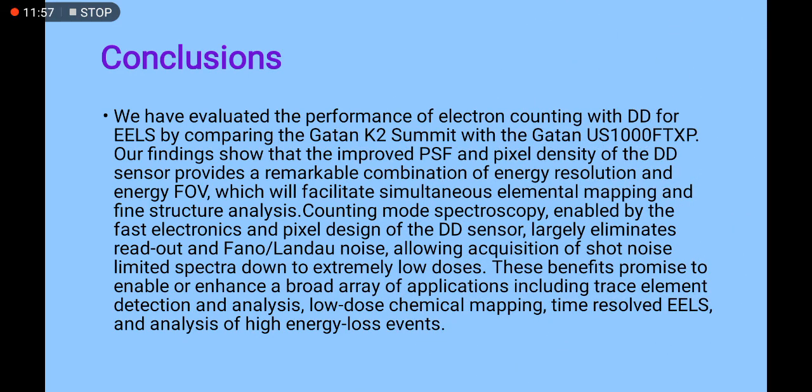Now I will tell about the conclusion of the interpretation of electron energy loss spectroscopy. We have evaluated the performance of electron counting with DD for EELS by comparing the Gatan K2 Summit with a Gatan US 1000 FTXP. Our findings show that the improved PSF and pixel density of the DD sensor provides a remarkable combination of energy resolution and energy FOV, which will facilitate simultaneous elemental mapping and fine structure analysis.